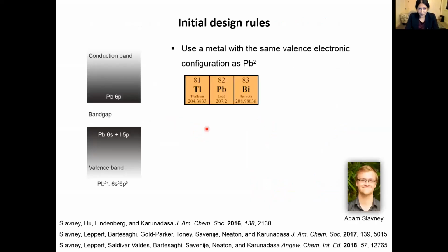So if someone posed this problem to me, and I knew nothing about photovoltaics, and I knew nothing about perovskites, and someone just told me, hey, what ion is going to act like lead 2+, I'm going to pull my periodic table out, as would many of you, and say, well, thallium 1+ has the same electronic configuration as lead 2+, as does bismuth 3+. So if you look at the band structure, a very simplified band diagram of the lead perovskites, you see that the valence band has lead s character, filled 6s orbitals, and the conduction band has empty 6p orbitals. So thallium 1+ has the same electronic configuration as does bismuth 3+. Thallium, in general, is more toxic than lead, 10 times more toxic than lead. Bismuth is non-toxic, right? Bismuth is even used in drugs.